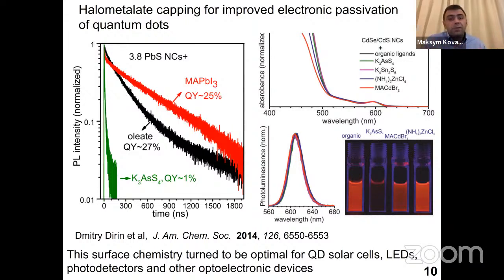So this on its own has become a very popular research area because you can have now quantum dots which are fully inorganic and which you can then electronically connect to each other, and they still maintain intrinsic semiconductor nature. So such quantum dots capped with halometallates are used in photodetectors and solar cells and some other applications. But we will not focus on those. We will just proceed with what we did as chemists. We understood that, okay, if a perovskite is good as a coating for the usual quantum dot, why don't we make the entire quantum dot out of perovskite? So that was our entry point into the world of perovskite quantum dots.